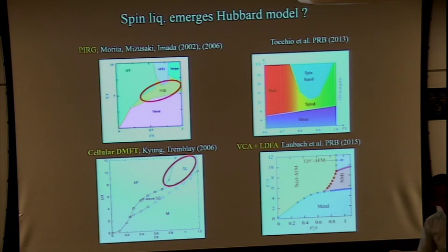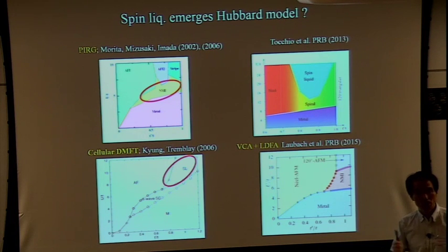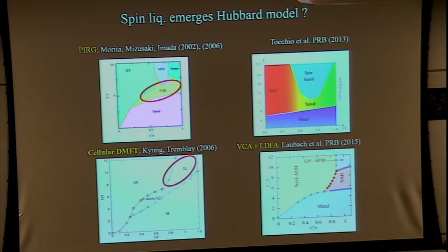This cellular DMFT also predicts a similar phase diagram. However, another group predicted that in triangular lattice situations there is no spin liquid - instead a spiral order is stabilized, but spin liquid resides in other regions. The idea is that in triangular lattice geometry, the 120-degree spin configuration is stabilized even at finite U, while in the square lattice it's a collinear Neel state. So in between these two spin configurations, the ordering is very unstable, and in such a situation spin liquid emerges. That is their claim, based on these numerical studies.